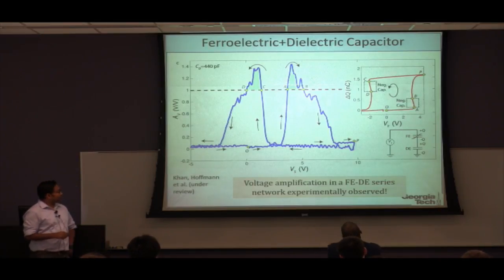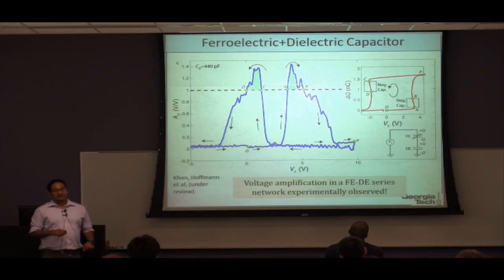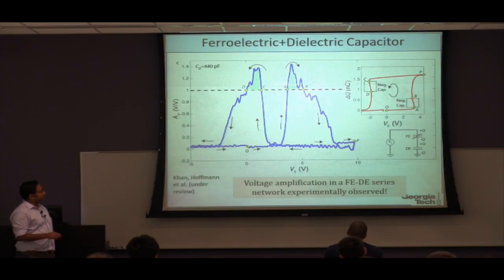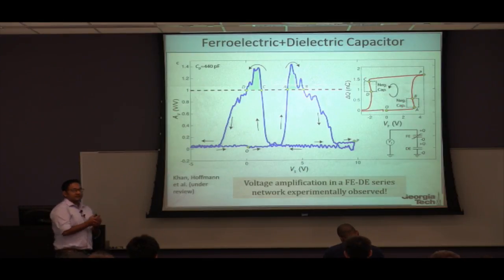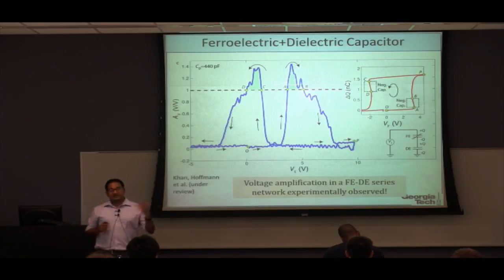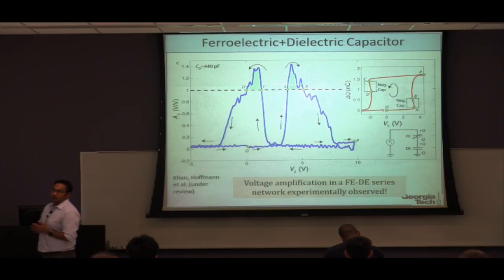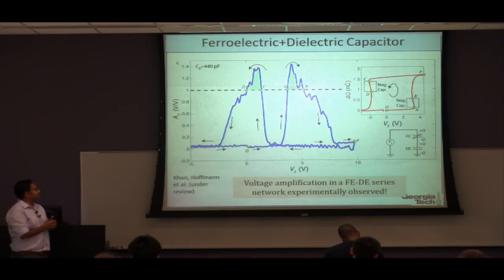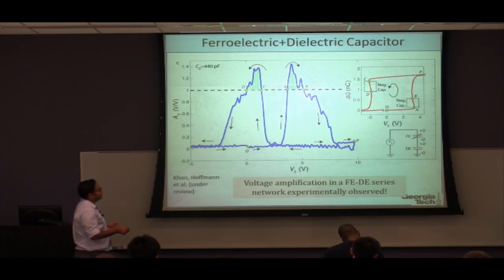And to confirm that this effect is real, we extracted the charge voltage characteristics in the system. And what we again see is that there is a certain region where the charge voltage characteristics has a negative slope, just like the previous experiment where we used a resistance and a ferroelectric and we got a similar kind of negative capacitance behavior. All right.